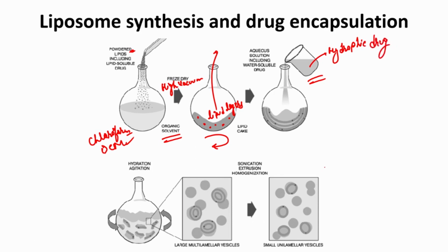and you just add it there and start mixing it. You can also heat it up. Most of the time, the lipids that are chosen have a melting temperature just above room temperature or just above body temperature, let us say about 40 to 50 degrees Celsius. So, you can heat it up so that they become more and more mobile and start to come off. As you give this agitation as well as hydration, these lipid membranes will start to peel off,